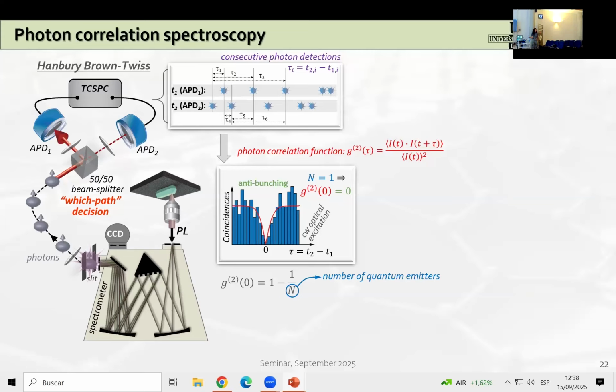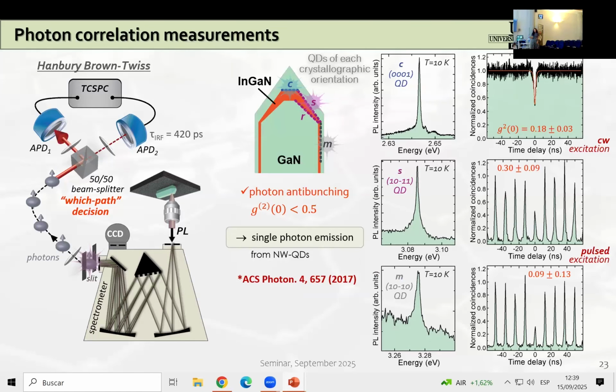And in the case of a truly single photon emitter, what we expect to see is that this g2(0) is completely vanished here at zero time delay. And this is because if we send a single photon to this beam splitter, it cannot divide itself, so we cannot obtain simultaneously, in the case of a single photon, counts at both detectors. Right. So indeed, if we perform these measurements on quantum dots of each crystallographic orientation, we do see such a reduction of coincidence rate at zero time delay here and here, so for polar, semipolar, and non-polar dots.